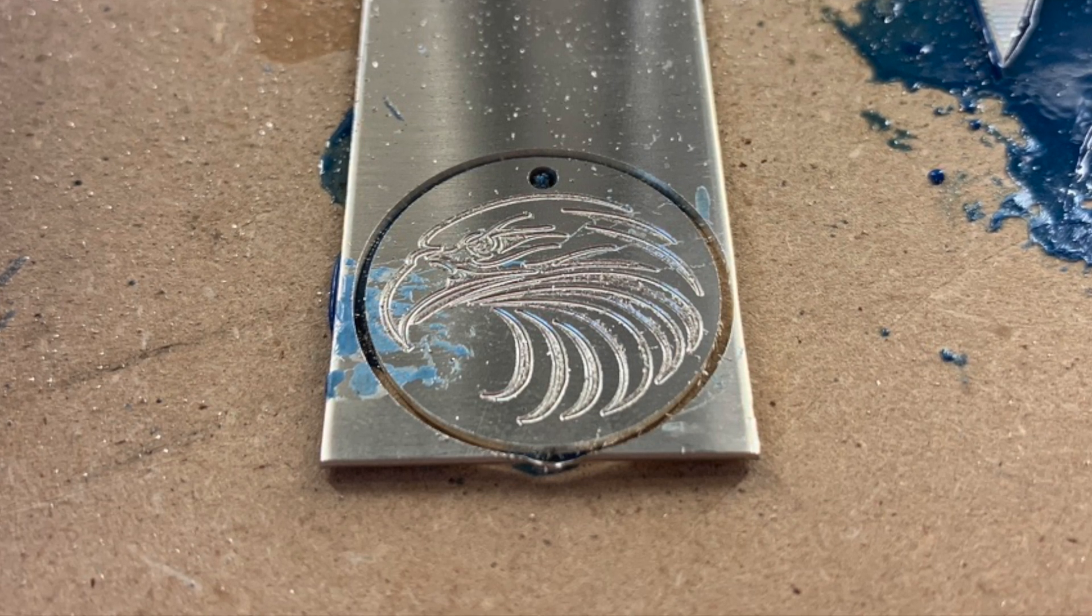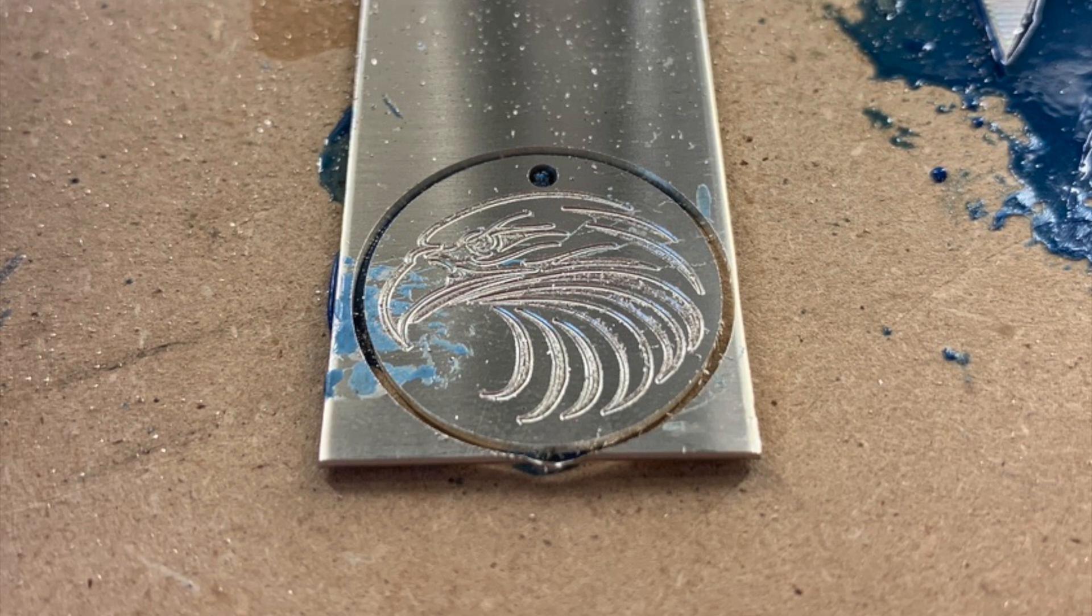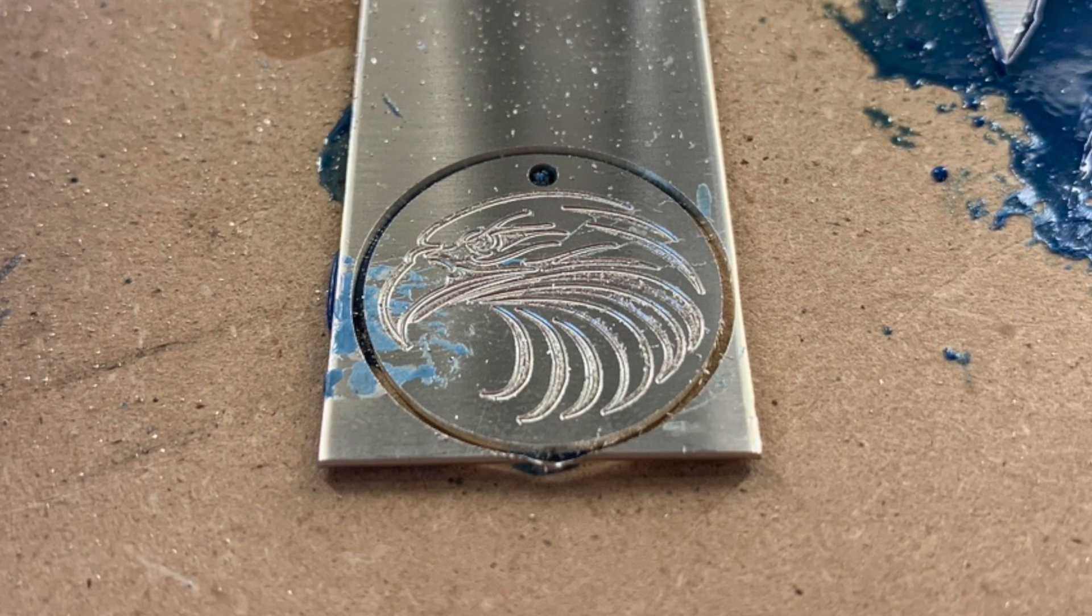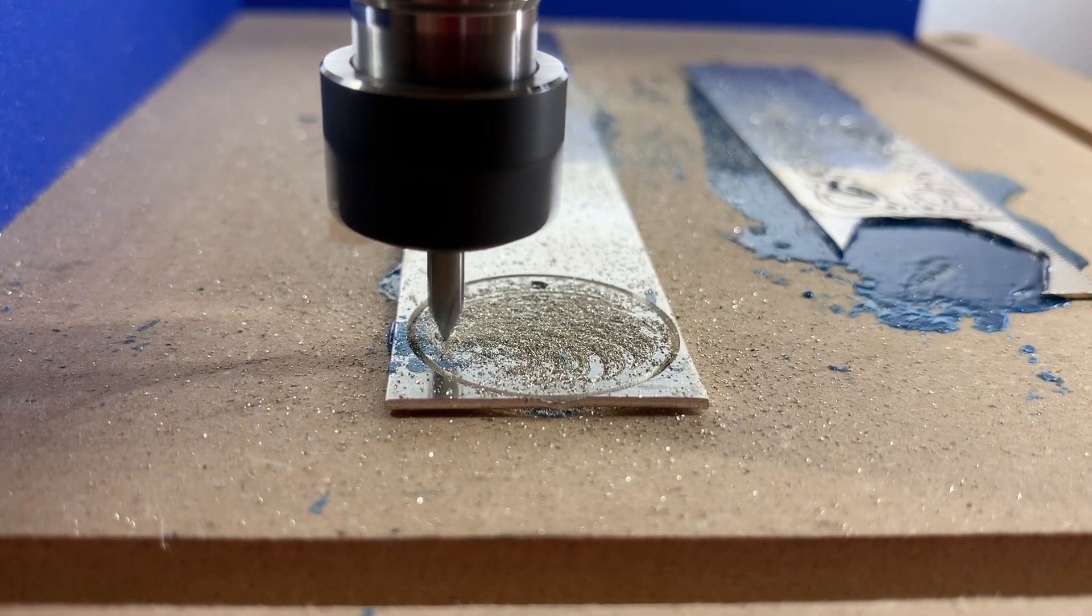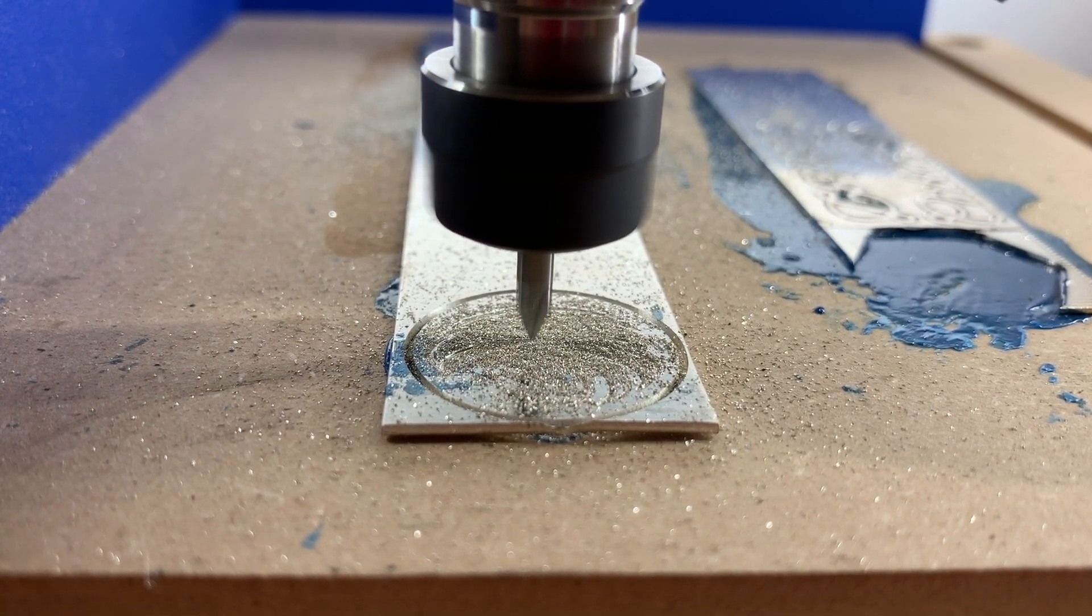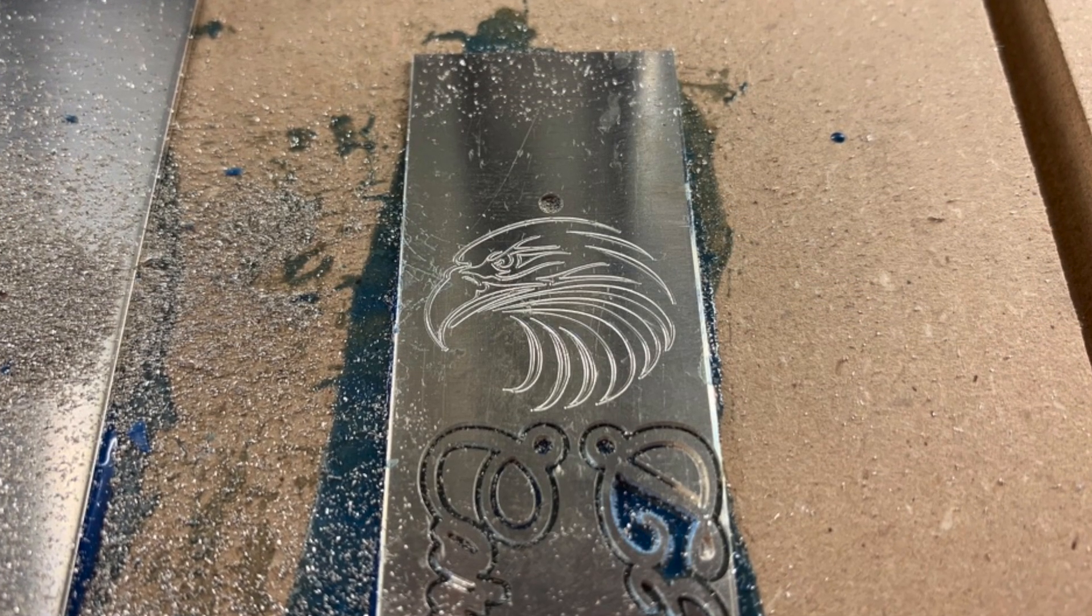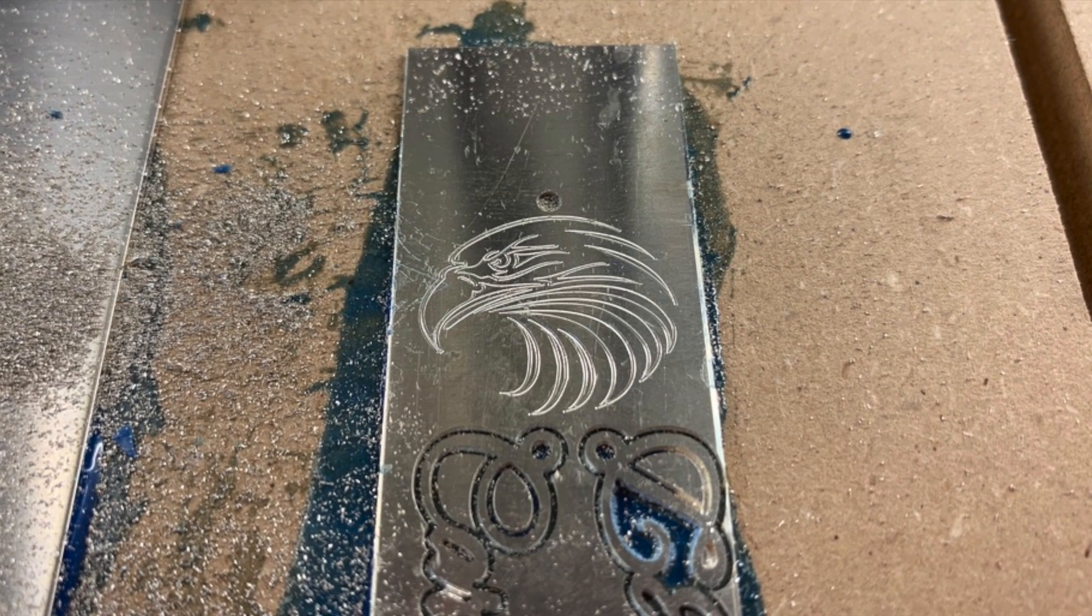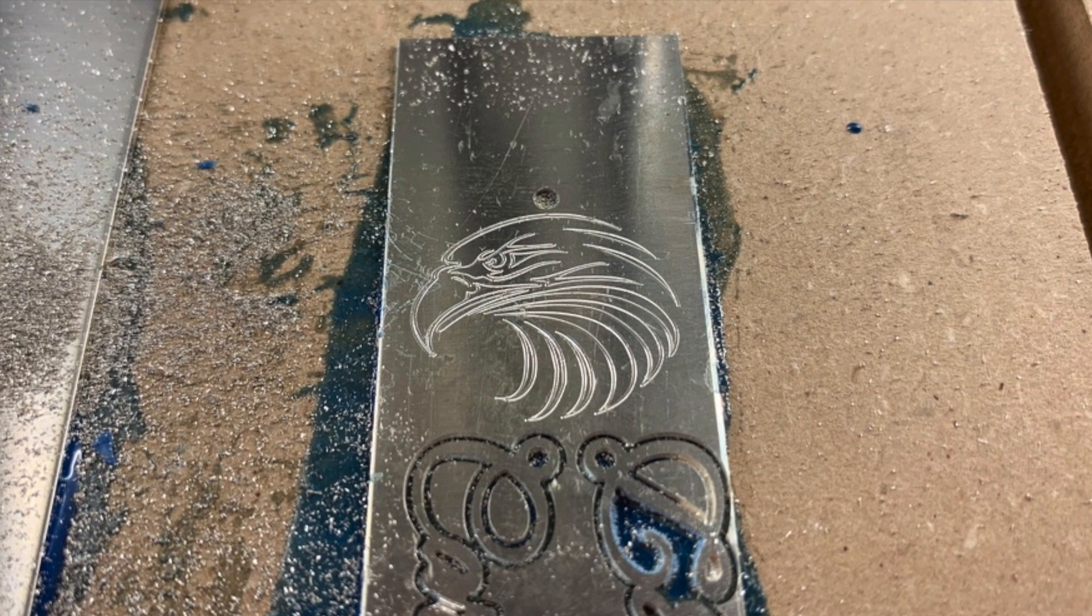The piece that I cut out can be polished up by hand, but unless you trace all the lines with a hand engraving tool or something, the lines will likely never be perfectly clean. Even though you can technically machine silver in most states of temper, harder is almost always better. This is the exact same toolpath run on some half hard silver, producing much nicer results.